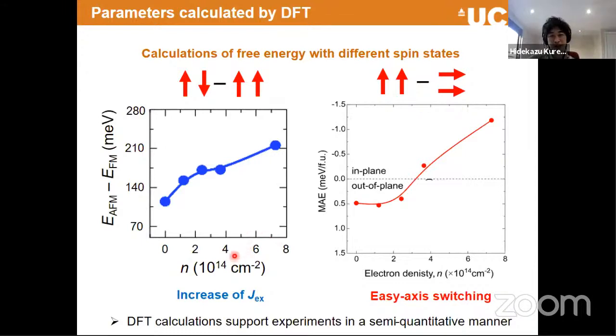So in the experiment, we found a 2D carrier density of about 4 times 10^14 per square centimeter. And then by calculating how many electrons per chromium we have, this is 25%. So we are looking at this regime. Okay. Yeah. We can discuss it later.